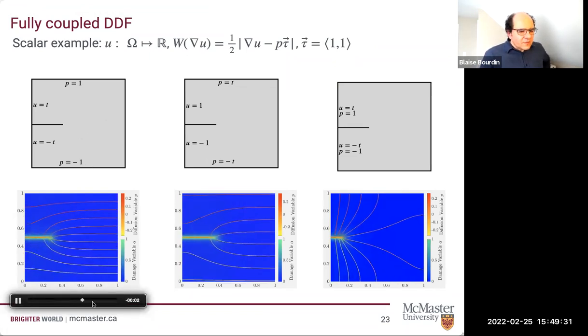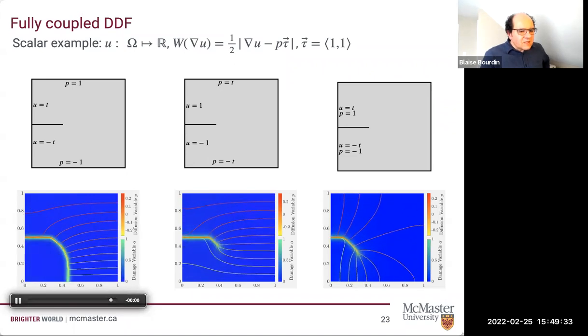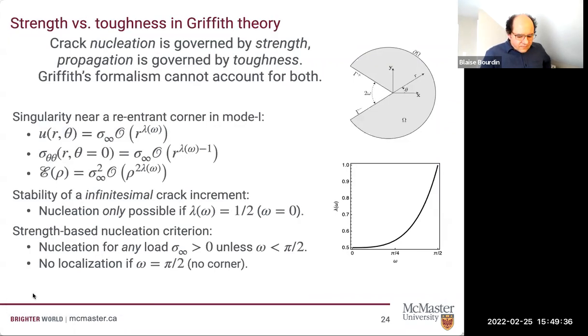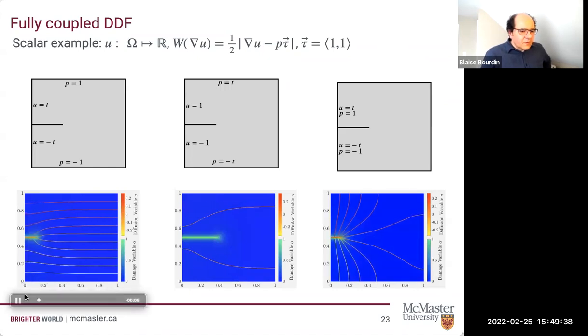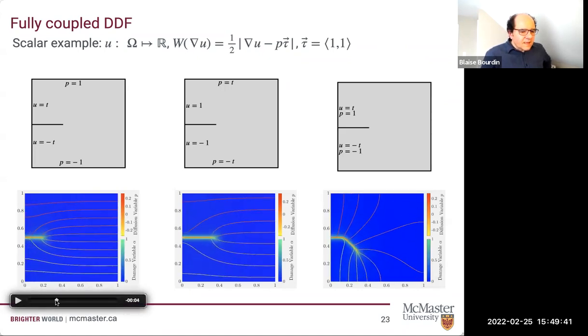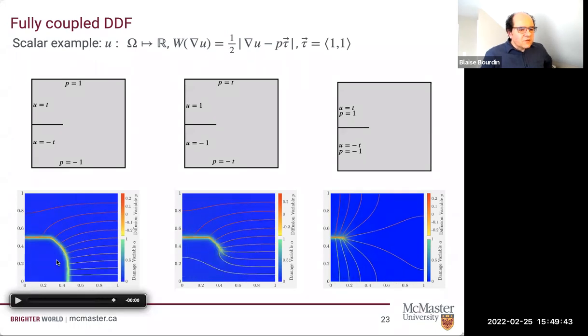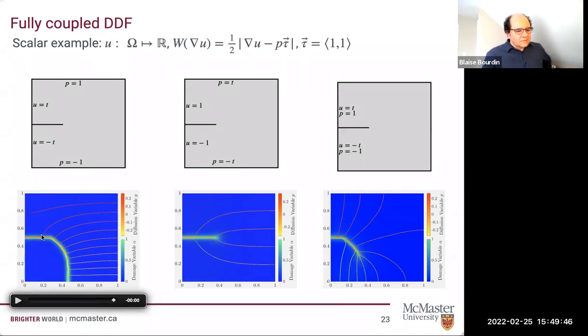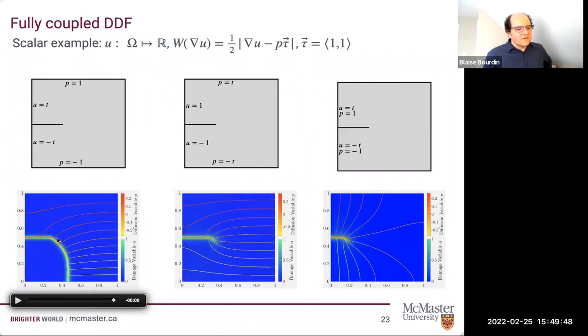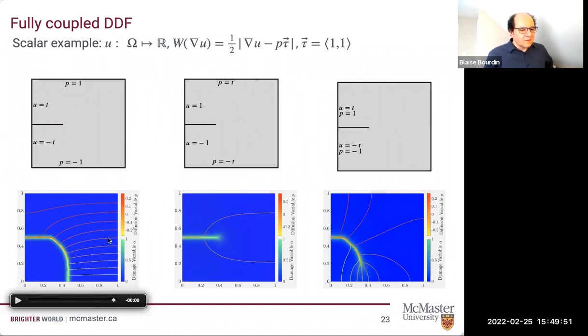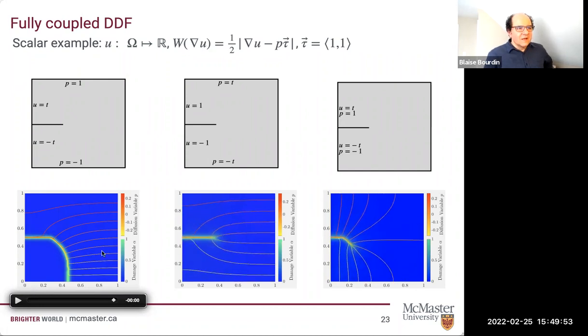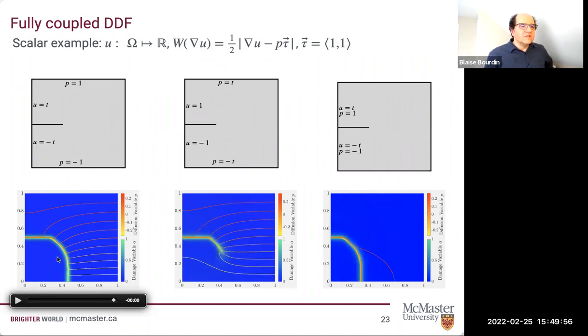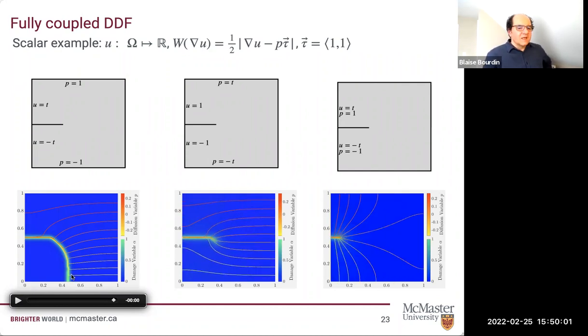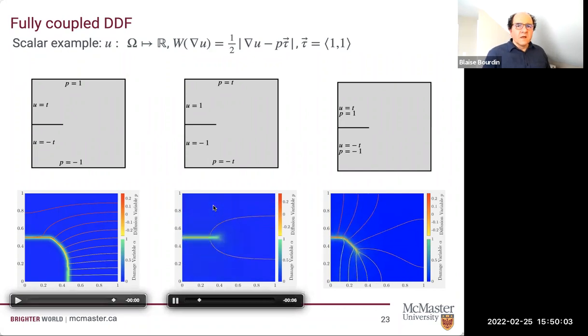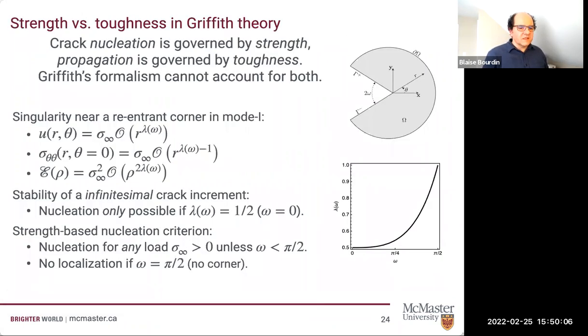So that's where you get this complicated pattern, but I just want to insist on the fact that you really see that this is a coupled problem simply by looking at this. You have a complex crack path, but the level lines of the P field are orthogonal to the crack near the crack. So it really means that you actually do recover dP/dn equals 0 along the fracture in the limit. Okay, I have 10 minutes.